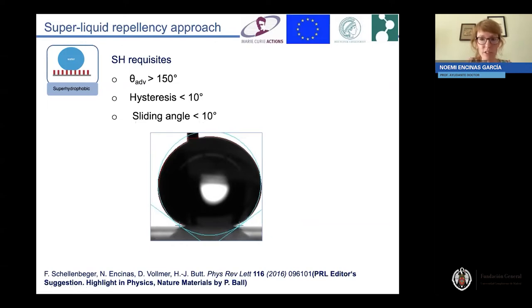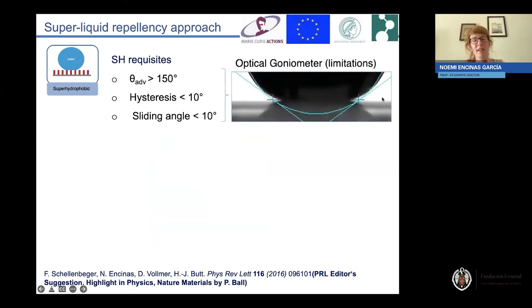So every researcher trying to design a good superhydrophobic surface has been normally trying to basically accomplish these requisites. But here, when I was working at the Max Planck Institute in Germany, we found the very first problem, or we basically asked ourselves whether we were measuring this correctly. Normally, contact angles are measured with an optical goniometer, which presents certain limitations. So we saw that even using different types of adjustments, we were not nicely measuring or exactly measuring the contact angle between the liquid and the surface whenever we were patterning this type of superhydrophobic surfaces.